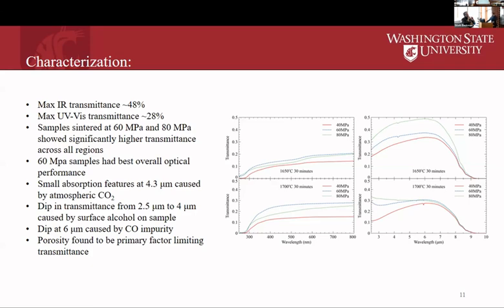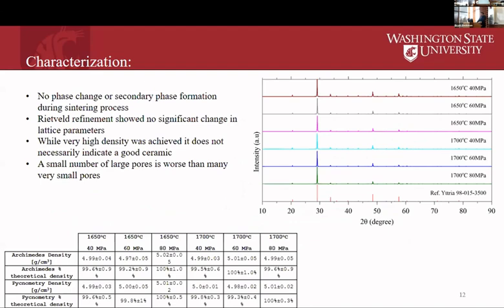As I said earlier, we were able to attribute the majority of our optical losses to excess porosity and large pores. So after we assessed the optical properties, we wanted to look at both the density and also the XRD again to see if any secondary phases happened.